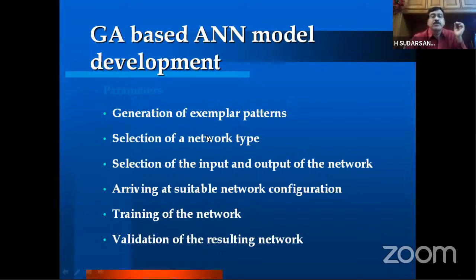Network type selection: we have used a feed-forward neural network architecture. The inputs are our water cement ratio, percentage replacement, and so on. The outputs are workability, the strength, and the durability. So we did a trial to arrive at the suitable network configuration. Then we proceeded to train the network using GA modified with the backpropagation algorithm.